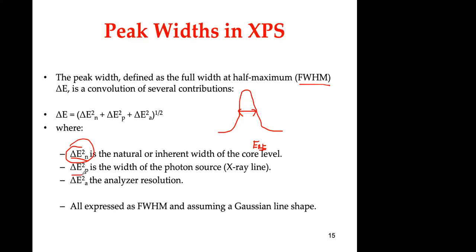And one is the source. You want an X-ray source that has a very small full width at half maximum of the emission, so a very narrow energy distribution. And also the analyzer: you want one that can resolve the kinetic energies as much as possible. These two parameters are the ones that you can control. So you get a better X-ray source and a better analyzer, and you can improve the full width at half maximum of your spectra.